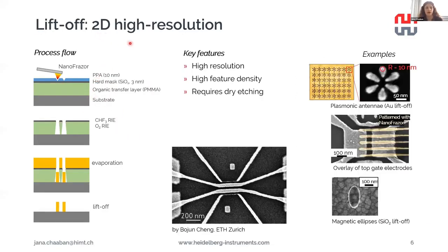And this is what we do in our high resolution liftoff method. So in this case, below the PPA layer, we use a spin coatable or even an evaporated thin hard mask. And we use this then to transfer the material onto the liftoff resist. And the reason the PPA is so thin is because this is also what affects the resolution of our features. Because as I mentioned earlier, actually the conical shape of our NanoFrazor tip is what defines the resolution. So you could see that the deeper you go into the PPA resist, the larger the features become. So it's important in this case to keep this as thin as possible.